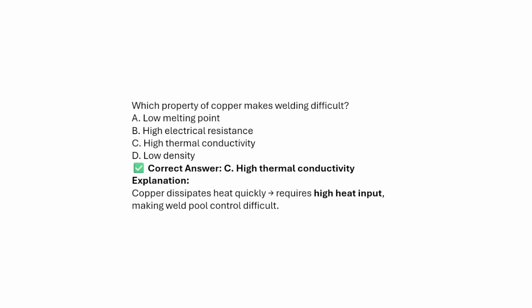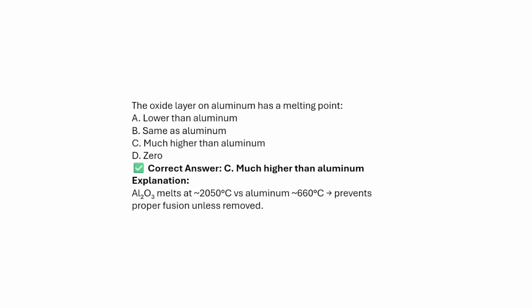Which property of copper makes welding difficult? Low melting point, high electrical resistance, high thermal conductivity, low density. The answer will be high thermal conductivity. So copper dissipates the heat quickly, requires high heat input, and makes weld pool control difficult. The oxide layer on aluminum has a melting point much higher than the aluminum. So Al2O3 melts at 2050 degrees centigrade, while aluminum melts at 660 degrees centigrade. So it prevents proper fusion unless removed.